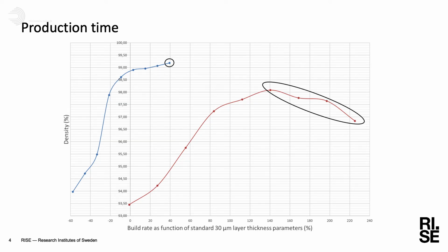And when you say much faster, how much faster can we achieve a fully dense part using this process with high-speed printing in combination with high-pressure heat treatment? So what we could see was that we could print with almost 150% faster production rate using a faster laser speed and higher layer thickness. Wow. So that's a really good improvement, especially when we're talking about printing big parts that can take several days. We can decrease the production time a lot.